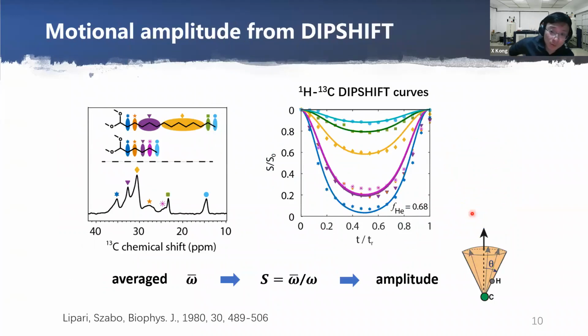While deuterium NMR is very helpful to offer the general picture, it is relatively difficult to derive more elaborate values of the motional amplitude. The dipolar shift experiment can measure the residual CH dipolar coupling after motional averaging. Based on classical analysis, we can calculate the order parameter and get the motional amplitude of the CH bond.